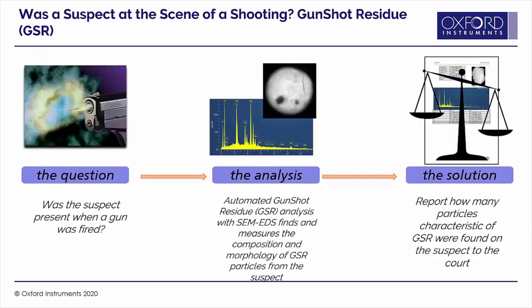Our final example is in the forensics field: gunshot residue. Gunshot residue particles form from the condensation of the vapour cloud which is formed when a gun is fired. The vapour cloud includes the combusted remnants of the primer of the bullet, and as it condenses, these particles can land on the hands, face or body of the person who shot it or anyone in close proximity. Particles can be anywhere between 0.2 of a micron up to a couple of microns in size, and if found on a person they can be considered as characteristic of a gun having been fired. Owing to their size, they need to be found using the SEM, and their composition must be within certain ranges to be considered as evidence — making this a perfect application for automated feature analysis.